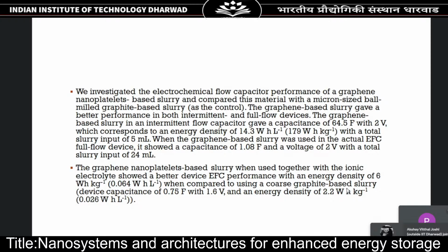And if you use it in a full flow device, then you get a capacitance of 1.08 farad. And we also saw that if you use ionic electrolyte, then we get energy density of 6 watt hour per kg. And this is much better than the graphite based slurry, which only gives about 2.2 watt hour per kg.